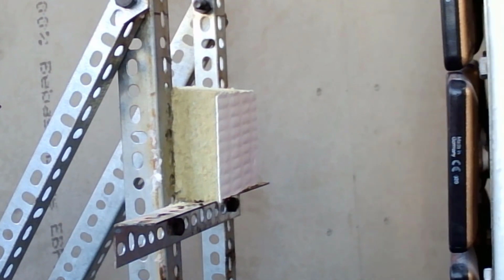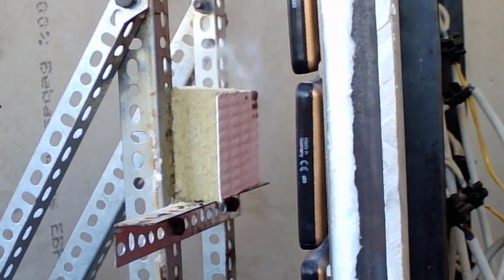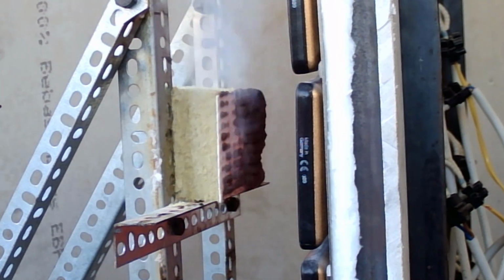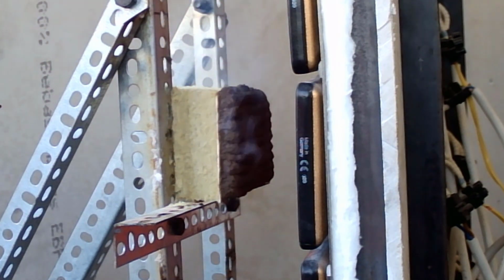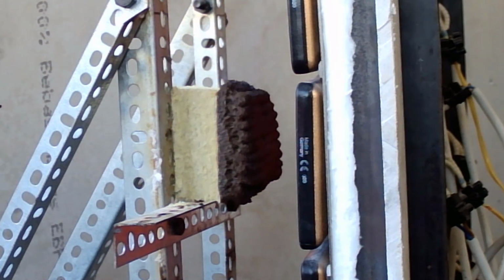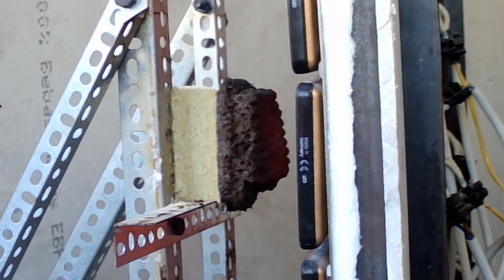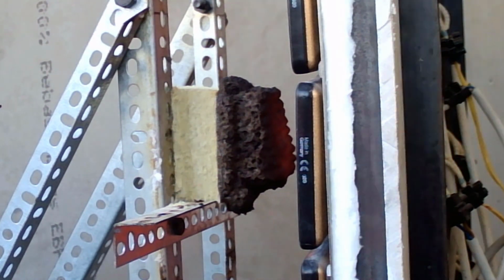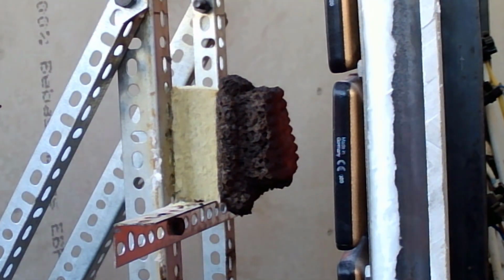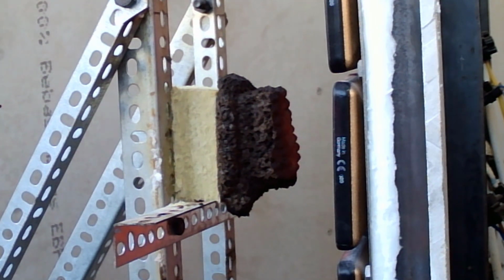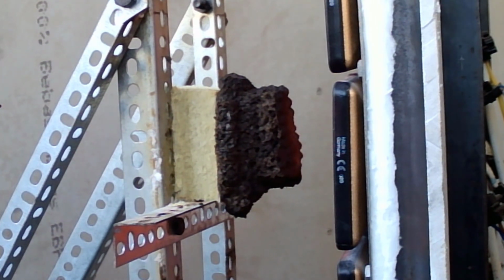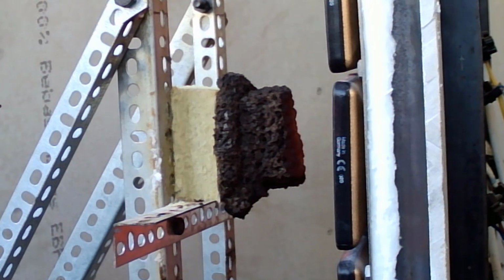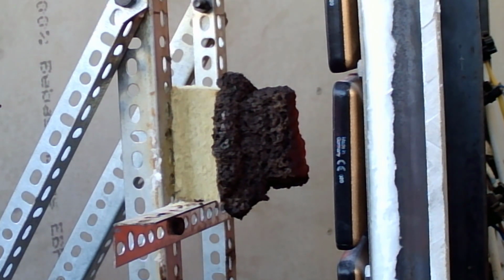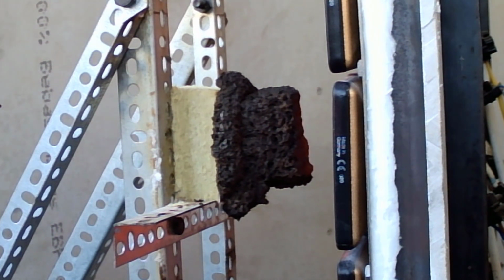The product here is for sealing around openings in floors and walls. Firstly, you need to have a non-combustible substrate, so that foam or the sort of spongy material you see in the middle must not be able to burn. Sometimes it can. And then the intumescent on top activates and provides a protective layer to the system. And you'll just see how much some of these systems can expand. That was a thin film in the beginning, and by the end it was about 60 mils thick.